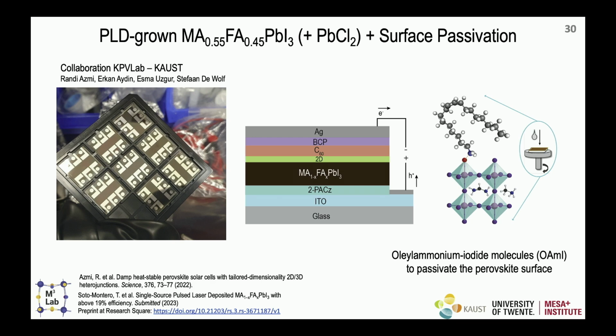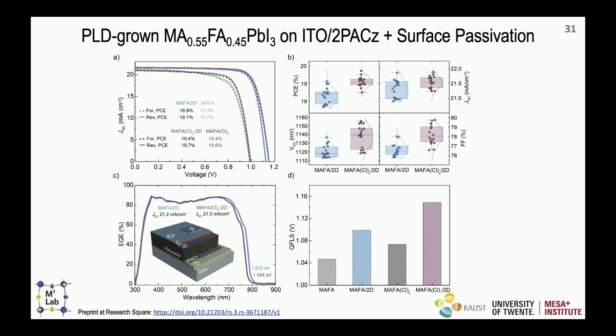And by basically doing that, we make many devices. This is how the devices look like, based with the PLD perovskite, and then the passivation and the contacts. And by doing that, we basically went from the standard device that we used to have, 14%, up to above 19%. So basically what we learn here is passivation is really, really critical. We can make a film at room temperature, but we still have some defects that we could actually passivate nicely. And if you see here, there is basically no hysteresis. And the most important improvement is very clearly in the VOC of the device.